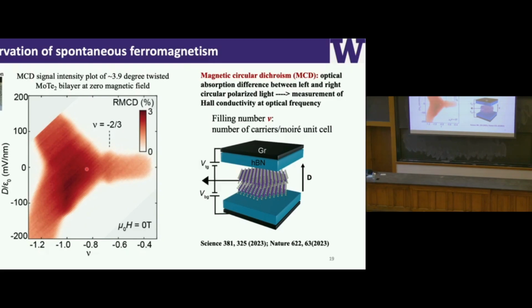So let me just introduce the experiments. The cartoon right here shows the sample we have. I have a twisted MoTe2 bilayer with a dual-gated structure. We have a top gate and a bottom gate, and these two gates can control the carrier density in the sample. We can also control the sign of these two gates and give rise to an electric field across the bilayer.